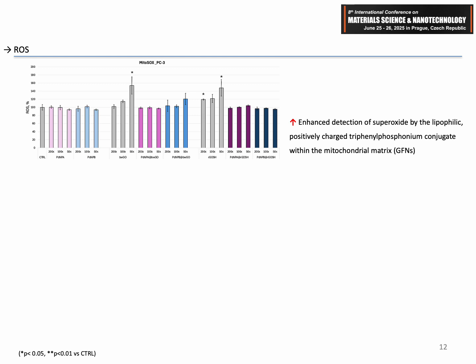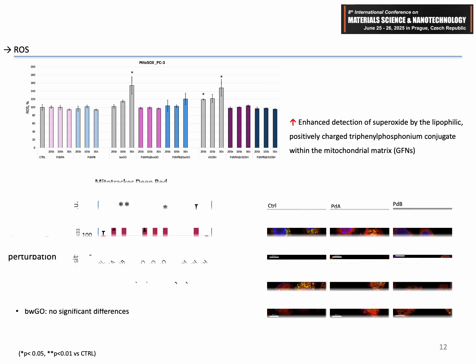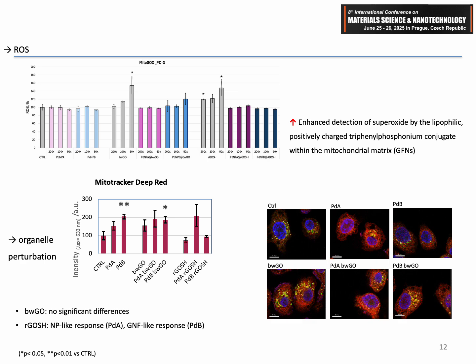As for the MitoSOX assay, it reveals increased mitochondrial ROS production, and this rise is especially relevant in cancer cells, where these elevated oxidized species can trigger apoptosis via oxidative stress pathways. And the confocal microscopy imaging confirmed the cellular uptake and the localization of the nanomaterials within cellular compartments. And the degree of organelle disruption varied with the treatment conditions, which is also very promising for their dual use, both in terms of therapeutic impact and diagnostic potential, especially for the hybrids.